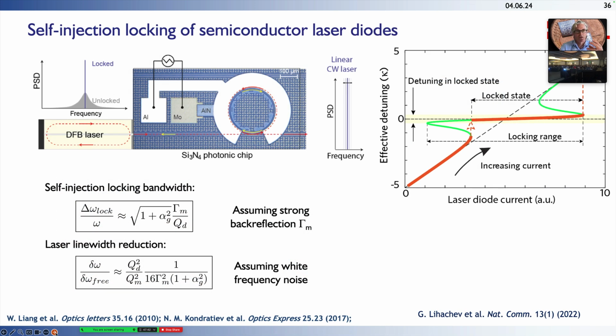So what can you do with this? One aspect that we have used this for is to create lasers that are frequency agile. The way we do this in one of the embodiments is we use a DFB laser, a very compact semiconductor laser, which in itself has a typically hundreds of megahertz wide free running linewidth. What we do is inject this laser into a silicon nitride microresonator with very high quality factor and benefit from the technique of self-injection locking.